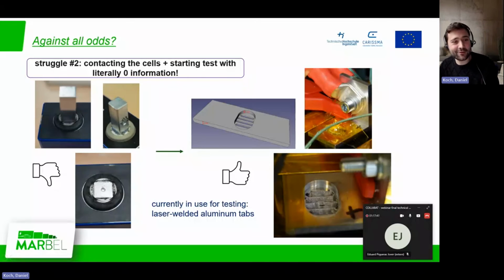And then the next struggle was to contact the cells, which is also an important point. Maybe we'll talk in a bit more detail later on as well. We tried first to laser weld rectangular blocks to simply attach test bench cables. But since we were targeting a very high current, we also needed very massive cables attached to the cells. And in this case, as you can see here in this picture, it was just not mechanically stable enough to account for the high forces occurring due to the cables.